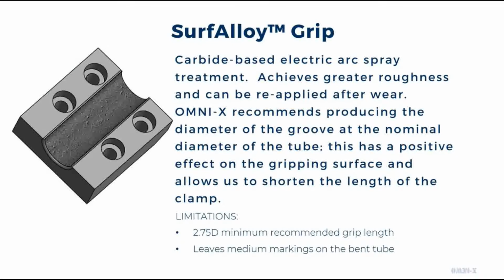Surfalloy is a carbide-based arc spray treatment that achieves greater roughness and can be reapplied after wear. OMNI-X recommends producing the diameter of the groove to the nominal diameter of the tube. This has a positive effect on the gripping surface and allows us to shorten the length of the clamp. Limitations of Surfalloy are a 2.75D minimum grip length is recommended, and it leaves a medium marking on the bent tube.